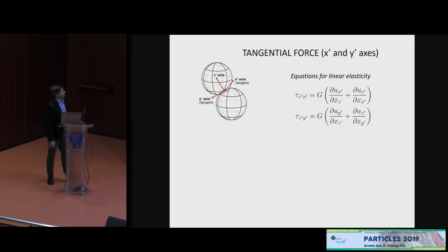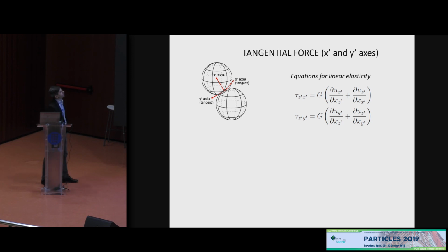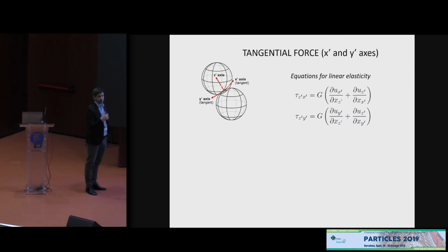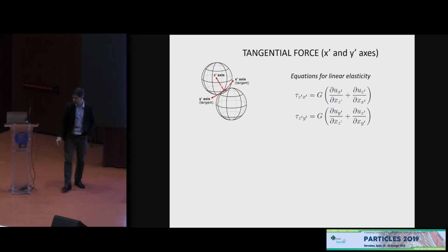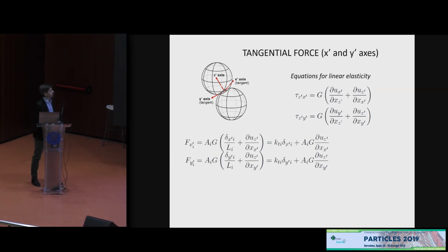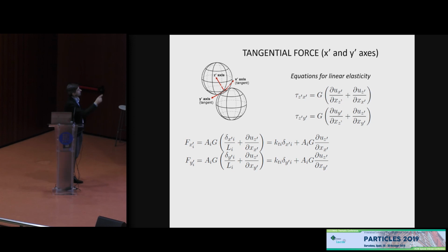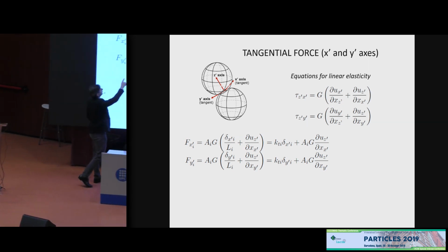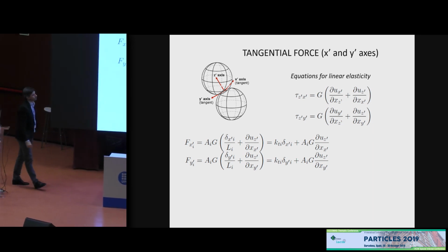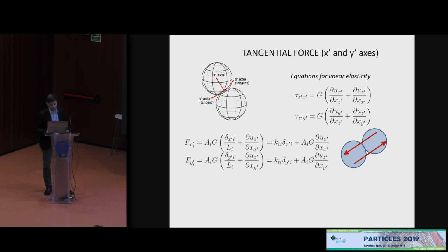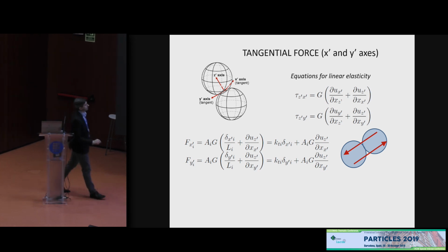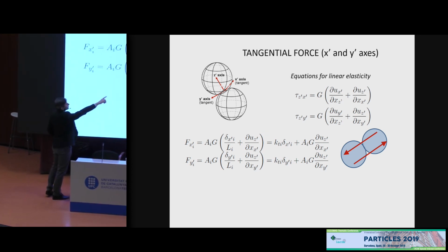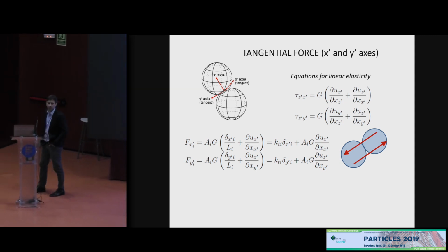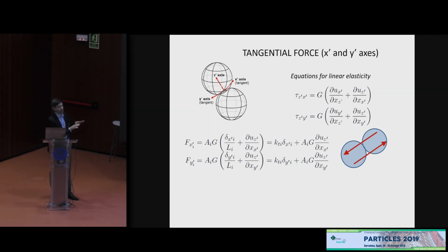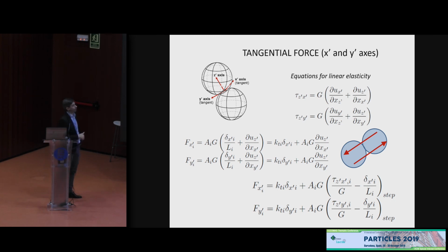Well, let's do the same then with the tangential force. We take the equations for linear elasticity for the tangential stresses, that's the expression of the continuum, and we do the substitution. Here we have that the forces in the lateral directions are some AG, and the two derivatives we are substituting in the same fashion that we do for the normal direction, and we need the last term, these two at the end of the formulas, that they are basically a measure of the shear strain along the bond, which is something that you cannot get from two spheres. That's impossible. So we feed that with the information coming from the stress tensor.